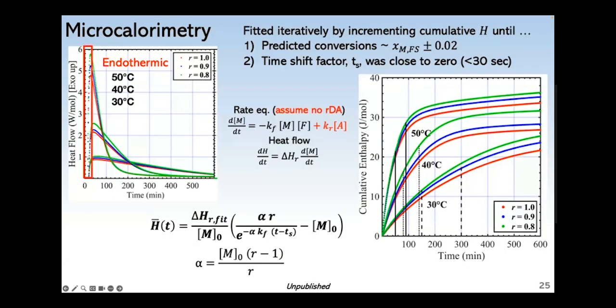And then I performed microcalorimetry on the same samples at the same temperatures. Here, I'll first bring your attention to the raw heat flow against time plot in the top left. We initially see net endothermic heat flow for the first 30 minutes or so because the instrument has to stabilize and initially samples take in heat to reach the testing temperature. But ultimately, I end up fitting the cumulative enthalpy on the right plot, which I've already corrected.